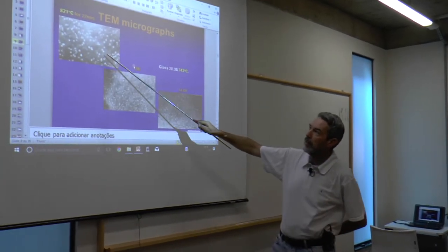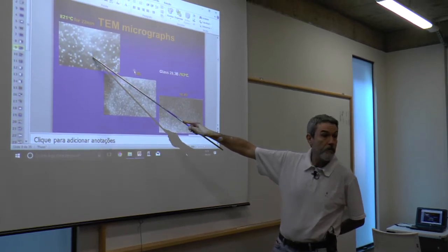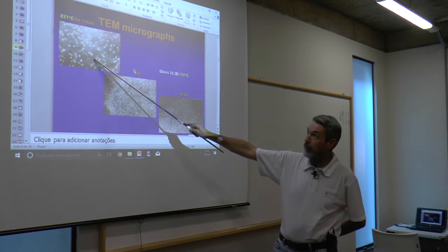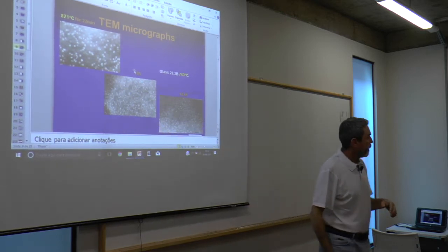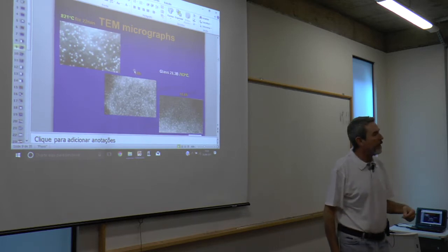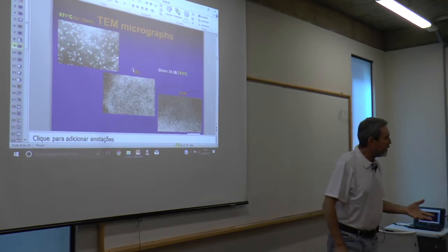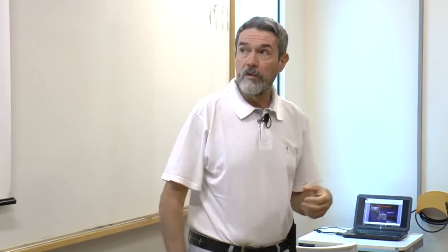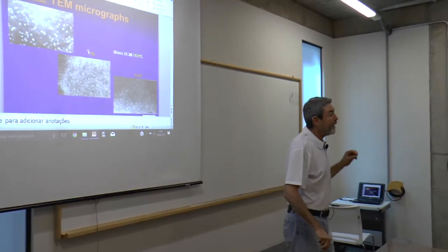Here, the white spherical particles are almost pure silica glass, and the matrix is a barium-rich glass. So some barium silicate glasses, lithium silicate glasses, sodium silicate glasses, calcium silicate, magnesium silicate, some borates, some phosphates. There are many systems which show this phenomenon, and sometimes it's difficult to detect.